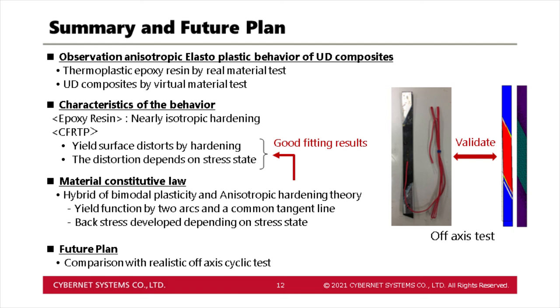In order to represent this material behavior, we proposed a new material model that combines the bimodal plasticity theory and the anisotropic hardening theory. The validity of this constitutive law is confirmed by the fact that it can accurately fit the response of virtual test. Our plan for the future is to implement a more robust verification process. Specifically, we will perform realistic cyclic tests of UD composite, where biaxial stress state can be created by changing the orientation of the fibers. By comparing the experimental results with the analysis results, we hope to be able to confirm the validity of our model in more detail.